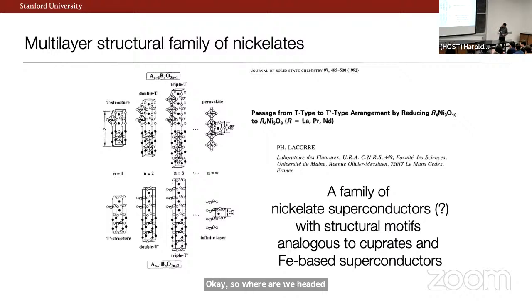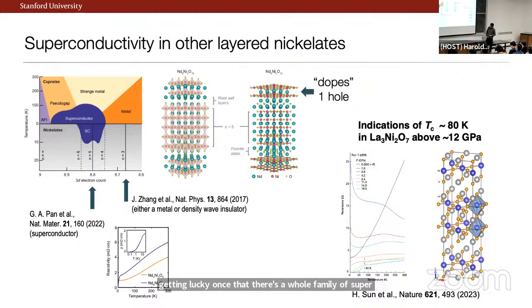So I actually told you a very small sliver of the material's phase space. Remember, I told you about growing a three-dimensional oxide, deintercalating oxygen planes, and making this infinite layer structure. What's cool is there's a whole bunch of different materials or chemistry themes. So you can make this one, or you can make 3 of these, or 2. There's a whole bunch of Legoland building blocks that you can find in this materials family. And similarly, you can relate that to these deintercalated structures. Now, this is work from far before superconductivity had been found anywhere. But we can ask ourselves, maybe it's more than getting lucky once, and there's a whole family of superconductors there.